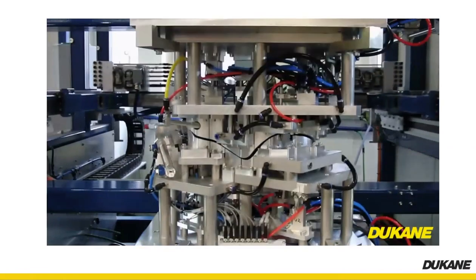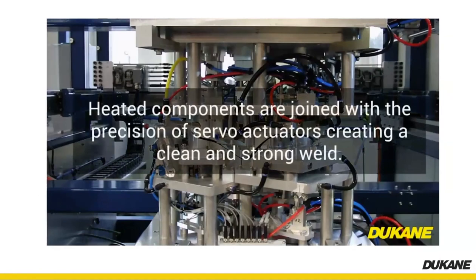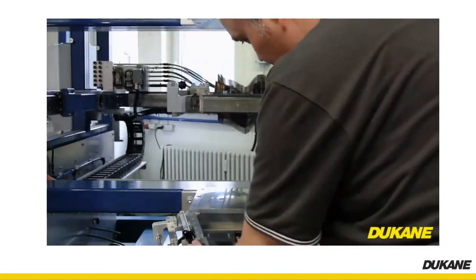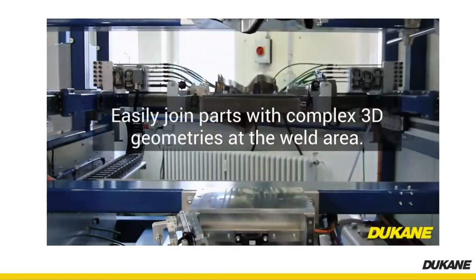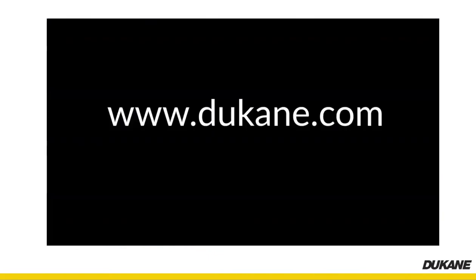Now, the benefit of this: with a hot plate tool, if your plastic part varies, we can't adjust it to match the contour. With an infrared tool, because the bulbs are quartz, we really can't adjust it to match your part contour. With a hot gas tool, we have all the benefits of those previous two technologies, but we can actually bend these little needles around very easily to perfectly match any variation in your plastic part. It is the only non-contact, high-temperature welding method in the world that can be adjusted, and the benefits of this are phenomenal, especially when you start doing things like intake manifolds for cars. Anybody who works in that industry knows how much variation you see there.